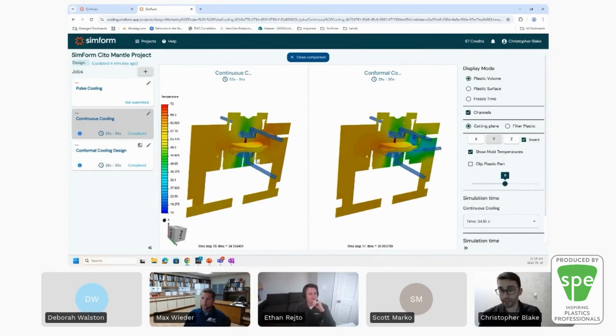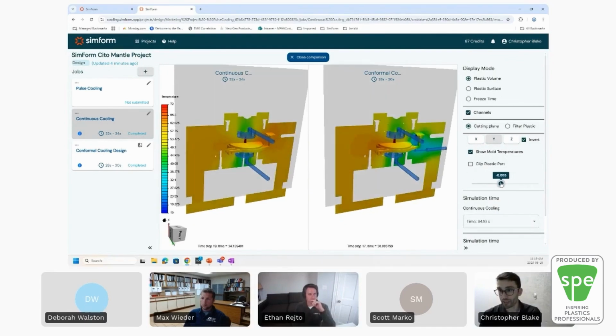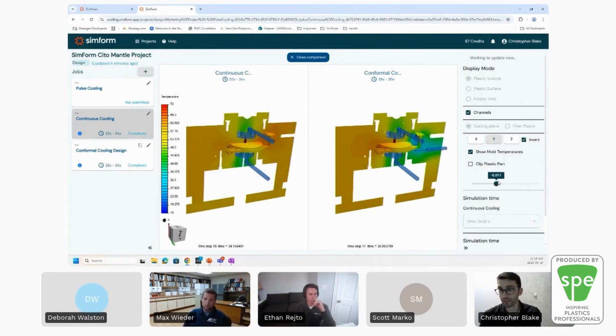So I can spin around and actually look at a cutting plane through the mold and have a look at the different temperatures through the mold. So you can see that it is actually much cooler now in the location of the handle, so that we're getting better temperatures, and it's no longer the hot spot within the mold. It actually has shifted elsewhere into the mold, as you can see right here.